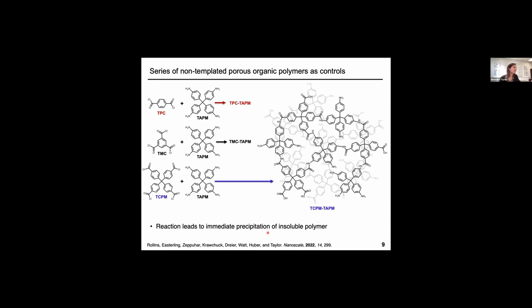All right, so we took this tetraamine and reacted it with a series of different acyl chlorides, a diacyl chloride, tri or tetraacyl chloride, to yield a series of different cross-linked porous polymers. And so it yielded a series of insoluble organic materials. This is, as I mentioned before, just a ChemDraw representation of what a hypothetical section of this particular polymer would look like.